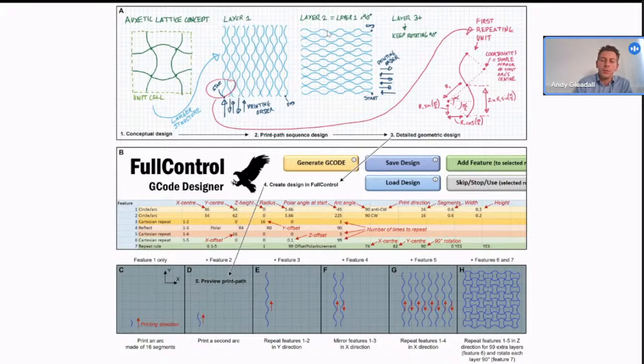We've also tried things like moving the nozzle up slightly and down slightly as we're going over a previously printed line. But in actual fact, we've just published a conference proceedings on it. The simplest and best solution we found was to print all of the vertical ones at one Z height, and then move up by half a layer, and then print all the horizontal ones. So you're only blocking the bottom half of the filament. Then you move up half a layer and print the vertical ones. So again, you're only blocking the bottom half of it. And that means you have the same conditions for the ones that are printed vertically and the ones that are printed horizontally. So you don't get this asymmetry where we were finding the strength in the Y direction was literally 4 times the strength in the X direction, just because of the sequence in which it was printed. Once we do this half layer offset, we've found that it becomes sort of isotropic in the X and Y directions. We have the same properties.